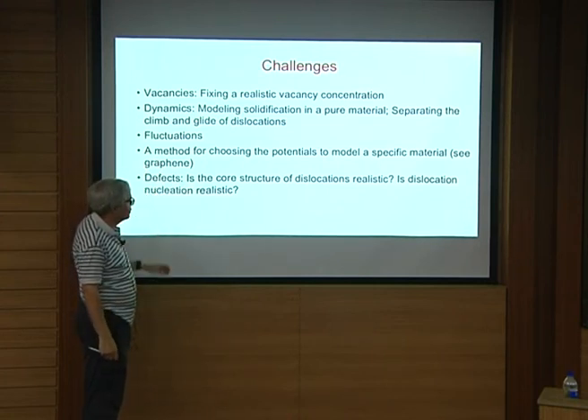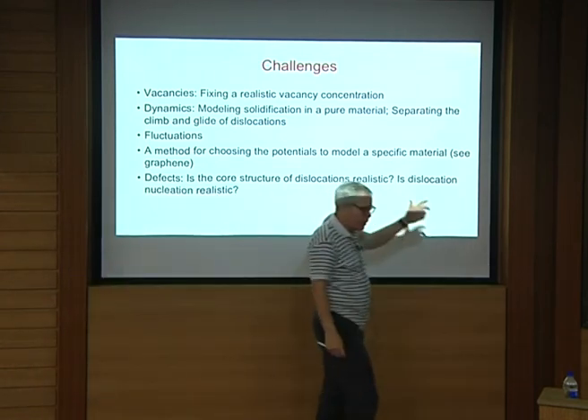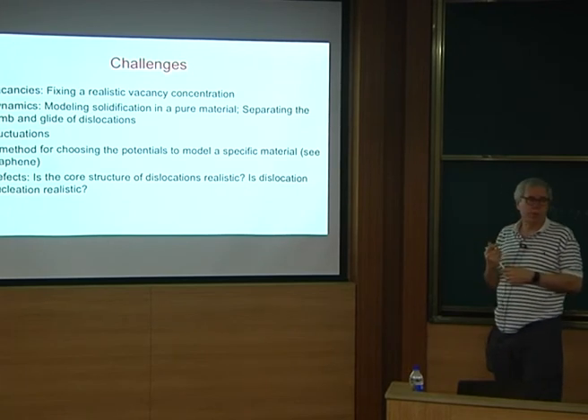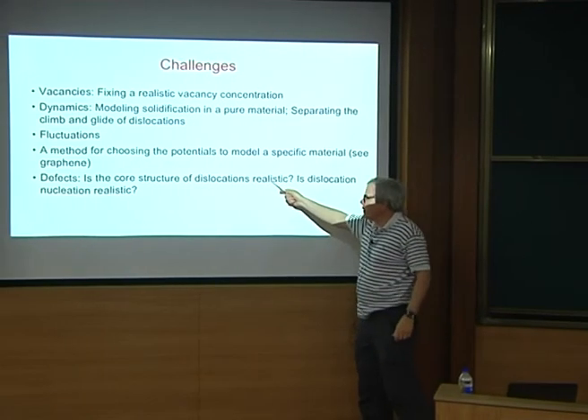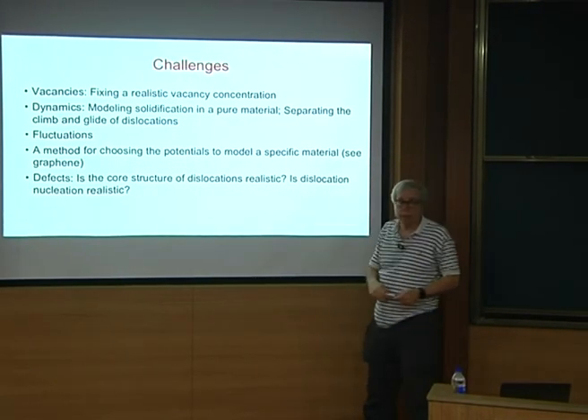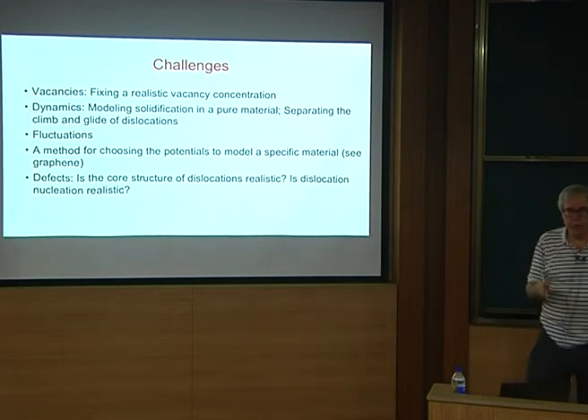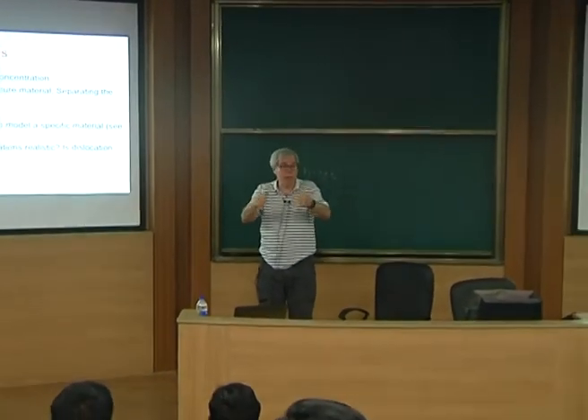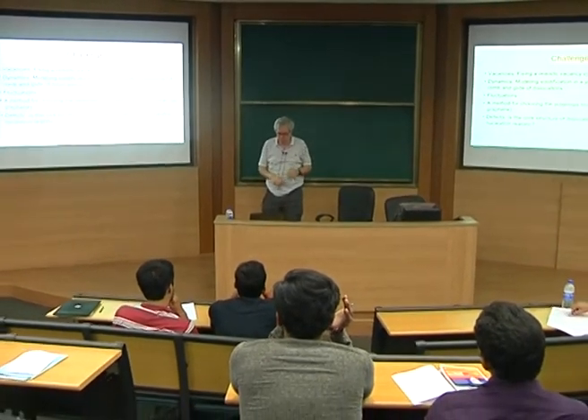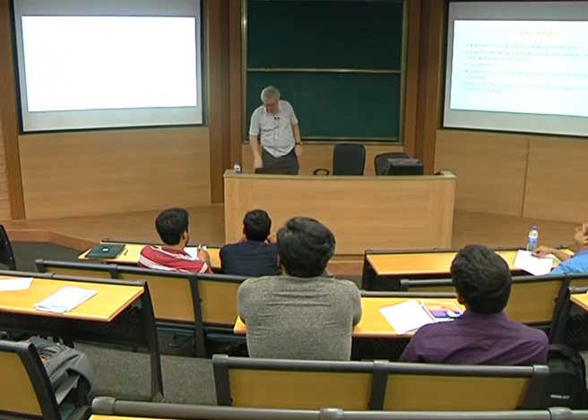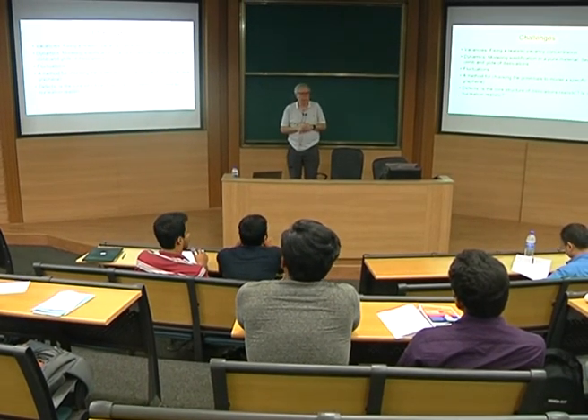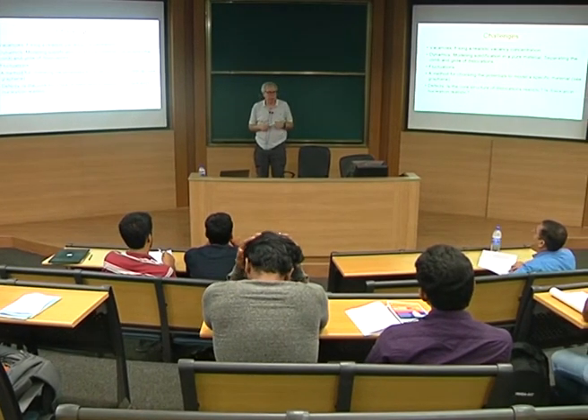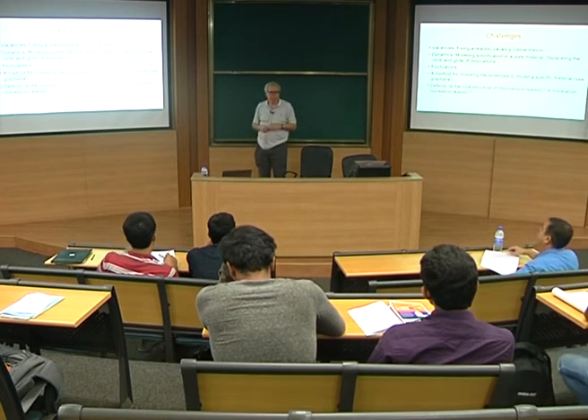That's the summary. This model is not yet at the point where you can easily use it for a given material. We're still finding out the strengths and weaknesses of the models, and there are significant challenges remaining. Any questions? In phase field modeling, you can put in fluctuations by making the equation a Langevin equation — adding random noise that models fluctuations of atoms about a lattice site. The problem is that with a realistic model of fluctuation energy, time steps go down to nanoseconds, but nucleation occurs on seconds — making it computationally intractable. What people sometimes do is increase the noise to unrealistically large values, and even then it's hard to get nucleation.